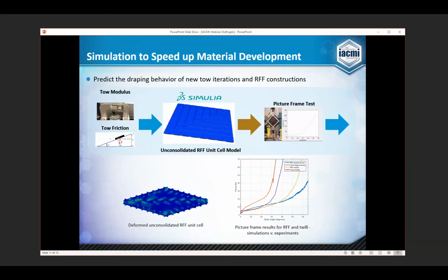That's what causes the wrinkles in our forming process. Well, because we don't have the interlocking behavior in the RFF, we don't see that same increase. There is some increase because of realignment of the tows for the force that's required to continue shearing it, but we don't see a really drastic behavior around like a 25-degree mark. So what this means is that when we move to our forming, we can accommodate much higher deformations, much more complex geometries in our part, and the computational models show that.